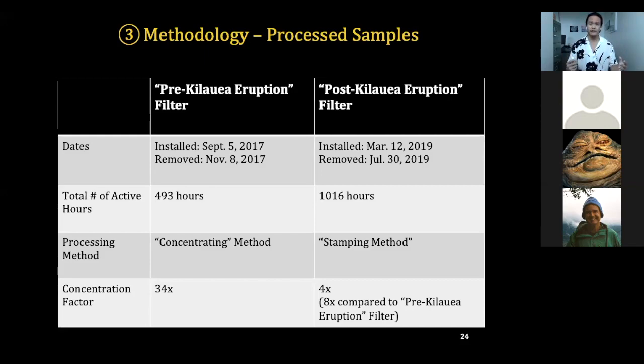As far as the concentration factor, the pre-Kilauea eruption filter has a concentration factor of 34, and we got that number simply by dividing the initial surface area of the big filter by the surface area of the small final sample. For the post-Kilauea eruption filter, the number 4 was from the amount of times we stamped our sample stub onto the exposed filter. However, as you can see, the post-Kilauea eruption filter was exposed for over twice as long as the pre-Kilauea eruption filter, so we multiplied that concentration factor by 2. So we have an effective concentration factor of 8 for the post-Kilauea eruption filter compared to the pre-Kilauea eruption filter.